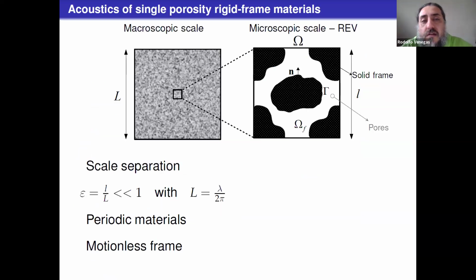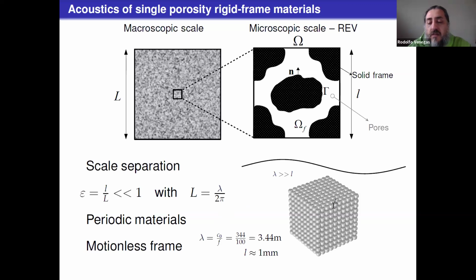Coming back to acoustics of single porosity rigid frame porous materials, here we have a diagram of the macroscopic scale, and if we zoom in, we get this representative elementary volume, or the microscopic scale, which is constituted by a solid frame in black here and some pores in white. Again, if we consider separation of scales with respect to, for example, the wavelength, which is related to this macroscopic scale through this expression, a granular material with a grain size of about 1 millimeter can be modeled as an effective fluid, because the wavelength for 100 Hz sound is much longer than this 1 millimeter grain size.